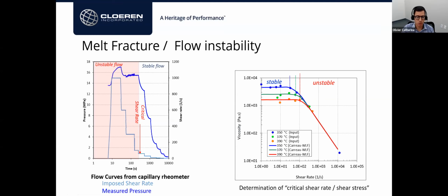I don't think it can, unless you are doing this type of experiment, and that's the whole point. That's one big feature of the capillary rheometer, I think, compared to rotational rheometers, where you can physically see the melt fracture. You can see the extrudate coming out and melt fracturing like crazy. You can see the stick-slip phenomenon. You can see when the flow is unstable. So that's how to anticipate it. Just looking at the molecular structure or the MFI value, forget it. You have to run this characterization.